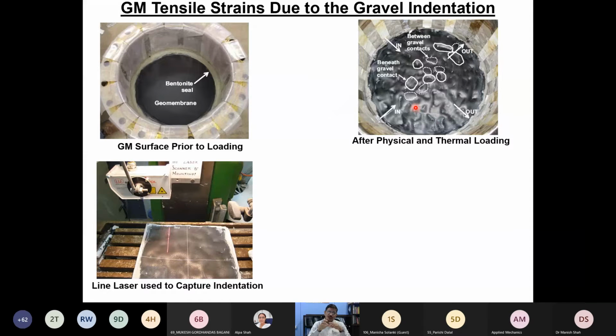In order to capture the in situ strain, we placed a lead sheet below the geomembrane. When the geomembrane indents, it pushes the lead sheet downward, and these are the indentations. Even after removal of the load, the geomembrane may rebound, but the lead sheet does not rebound. We froze this into plaster of Paris, and using a line laser we digitized the indentation. Then, using a protocol and a technique proposed by Rowe and others, we captured the tensile strain within the geomembrane.